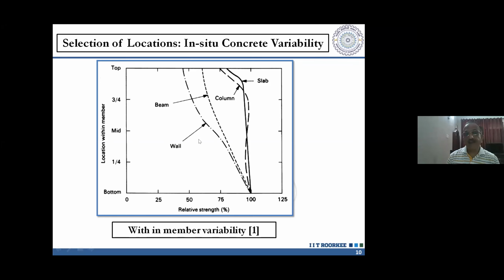Now, when you are doing compliance testing, meaning you are checking the compliance of the concrete, you will try to take readings towards the bottom side. I'm not saying exactly at the bottom. There are limitations of different methods of test. So keeping all this in mind, try to take readings towards the bottom, because if you take the reading towards the upper side, you will get a lower value of the strength, which is not the fault of the contractor. This is because of the hydrostatic pressure in the bottom side of the pour, because of natural reasons of gravity. When you do the concreting, the aggregates will try to settle down, and water and the paste will try to come up. This is not in control, it is a natural thing. So for compliance testing, you take the reading towards the bottom side.